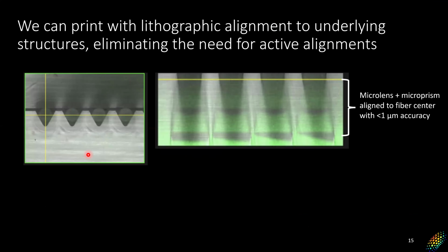And then we get this sort of lithographic alignment to underlying structures for free, which we think can fundamentally eliminate the need for active alignment. Our lithography tools are also essentially microscopes. So this is an example image where you can see a fiber array, which we've then printed these sets of lenses and prisms on top of. And these are aligned to the center of this fiber with sub-micron accuracy, because we need that level of accuracy anyway in order to build these optical systems.